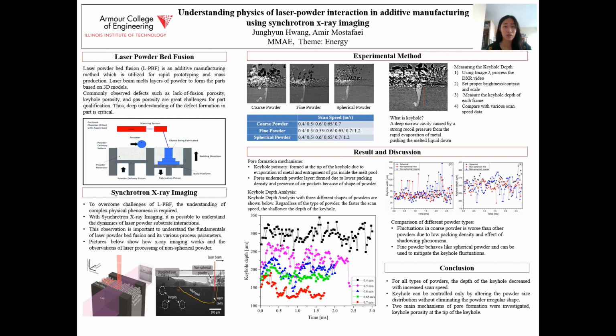In conclusion, the depth of the keyhole decreased with increased scan speed for all types of powders. Also, keyhole can be controlled only by altering the powder size distribution without eliminating the irregular powder shape.